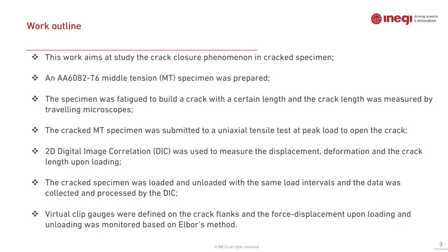So the work outline: this work aims at the study of the crack closure phenomenon in the cracked specimen. An AA6082-T6 middle tension specimen was prepared. The specimen was fatigued in order to build a crack with a certain length, and the crack length was measured by the traveling microscopes.